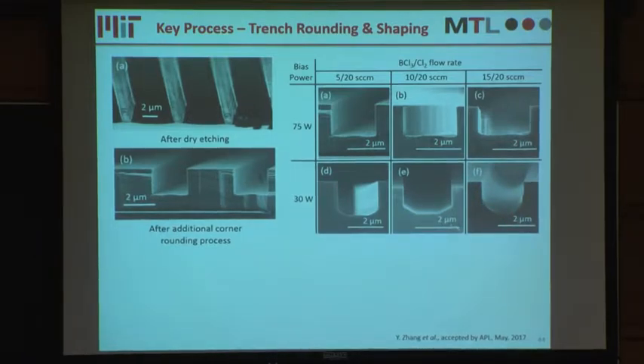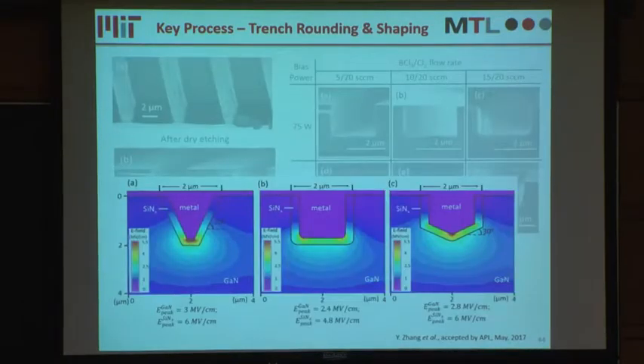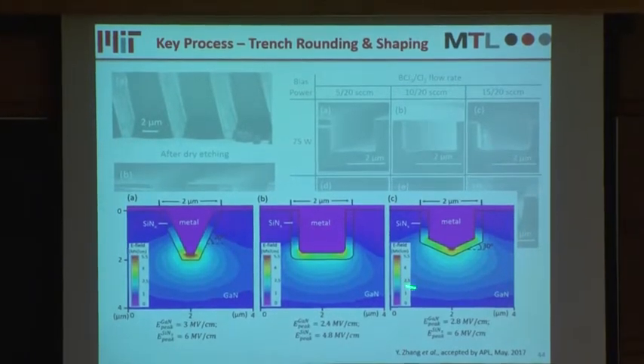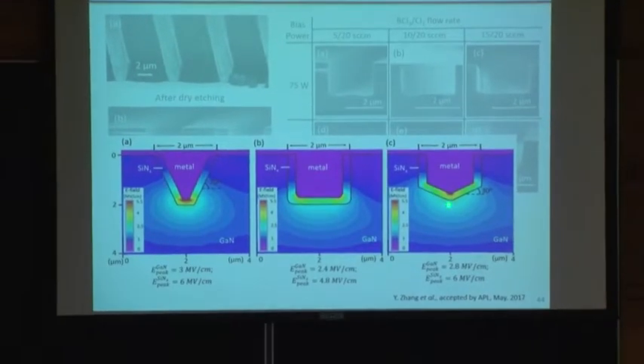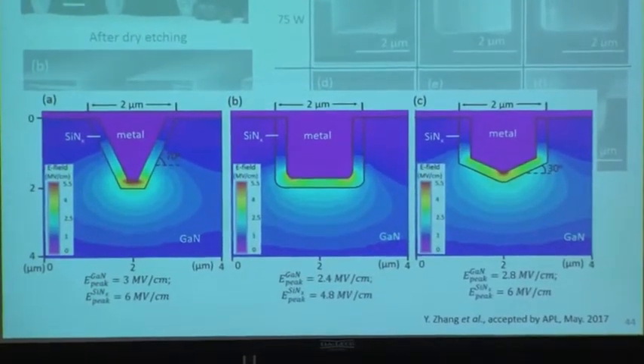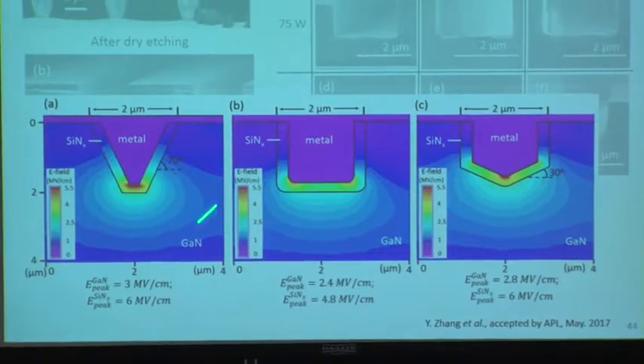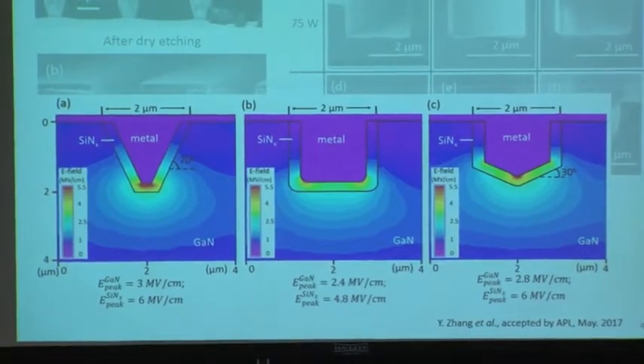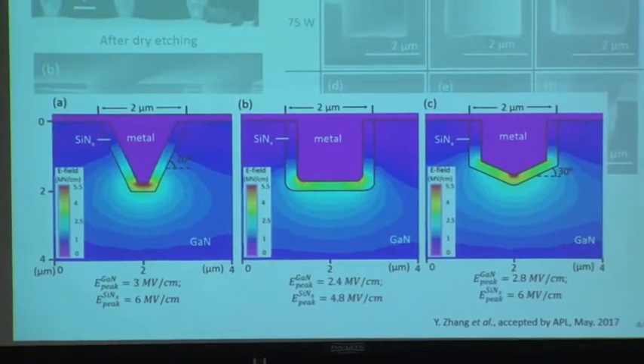To decide which shape would be best for the high voltage devices, we conducted simulations of 3 trench shapes: the trench shape without any rounding, the rounded flat bottom trench, and the rounded taper bottom trench. From the simulation, we selected the second one, the rounded flat bottom trench, as the shape to be used for the high voltage devices.